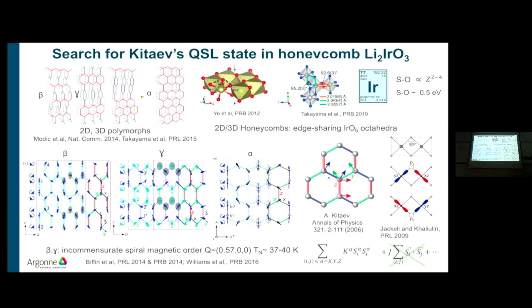So the order in this incommensurate spiral phase, and this is the incommensurate wave vector, that means that the periodicity of this modulation is not the periodicity of the lattice. So the magnetic scattering from this order will be separated from the lattice or charge scattering.